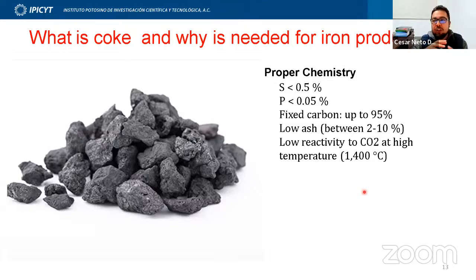And also it has a lot of porosity, but this porosity is macroporous, very open, like 1 to 10 micrometers, right? Also, one important feature of metallurgical coke is that it has very good chemistry for the iron refinery. For instance, sulfur and phosphorus are poison for any iron alloy and also for steel. If you have a little bit of sulfur or phosphorus in the steel, the mechanical properties of the final product will be very bad. You can break a steel shaft if you have a very high content of sulfur. And coke has very low content of sulfur and phosphorus, which means that it will not pollute the iron casting.